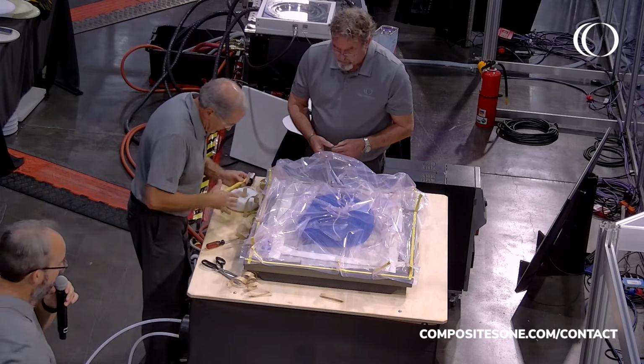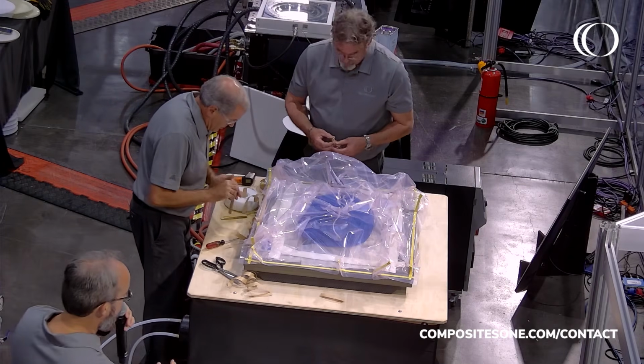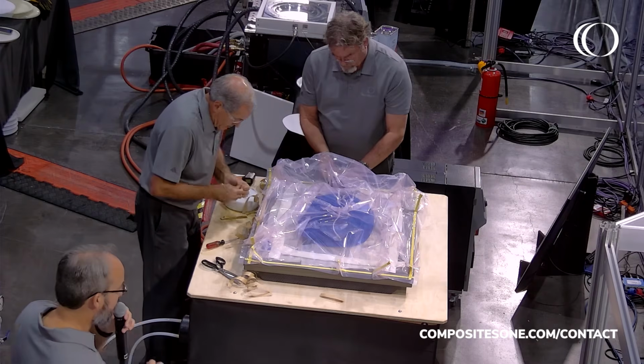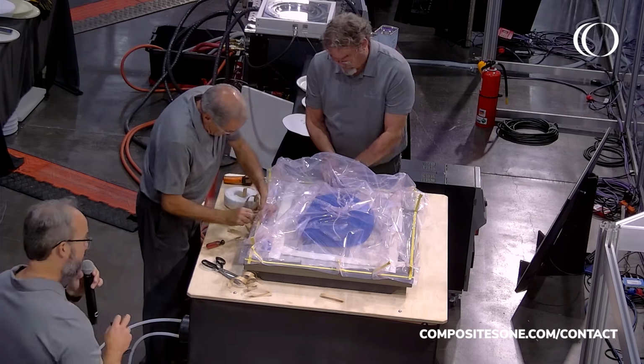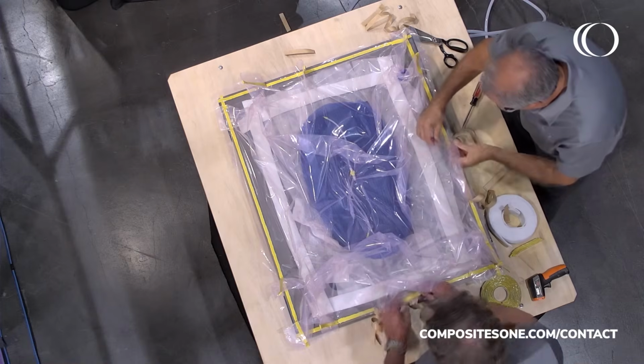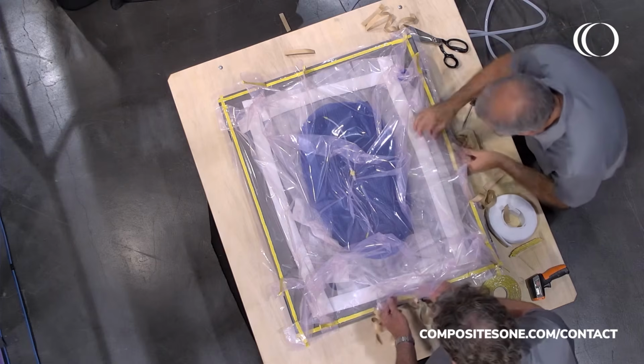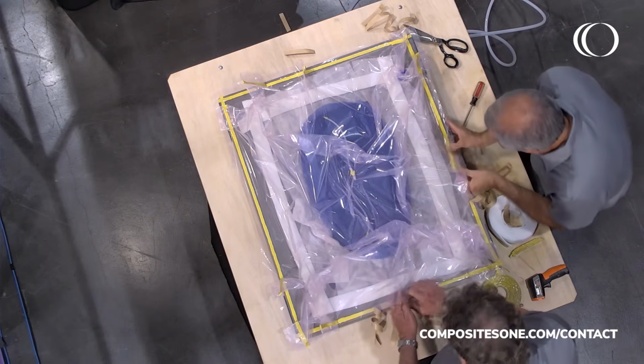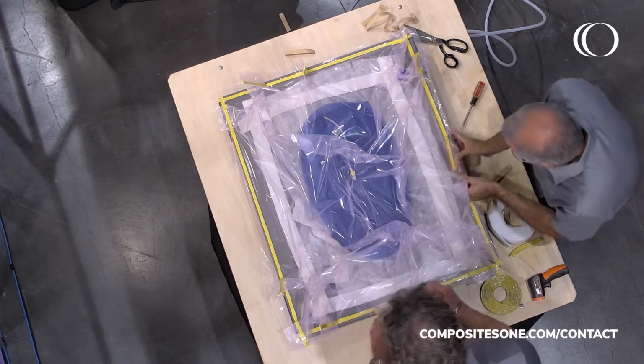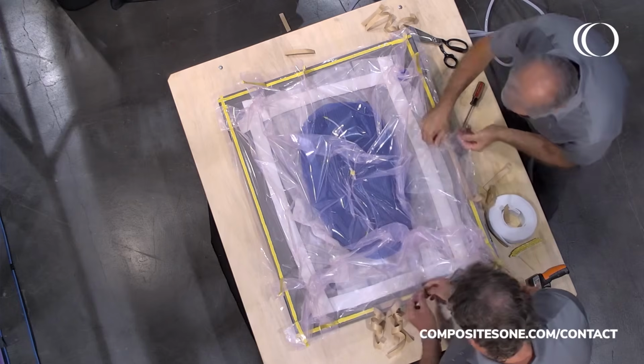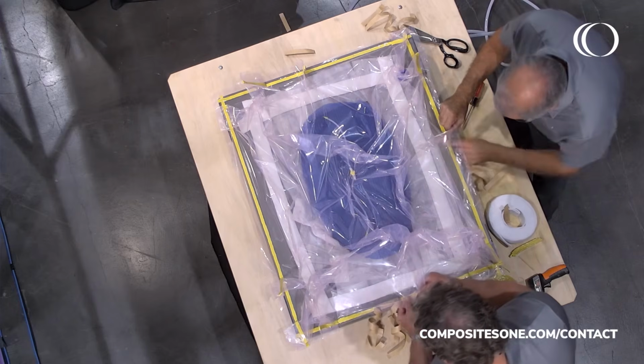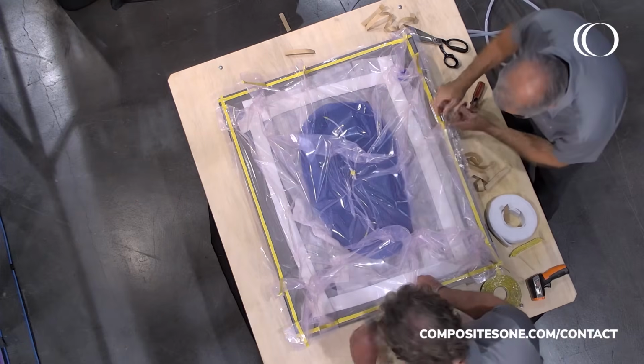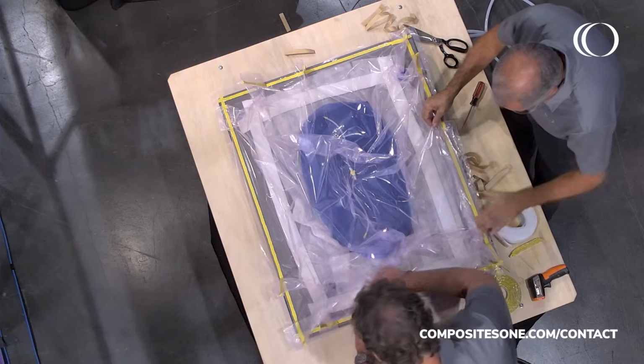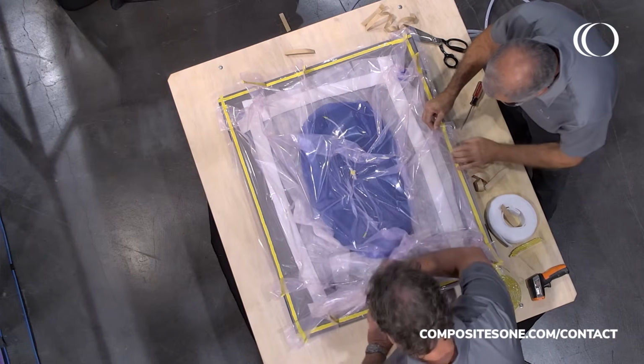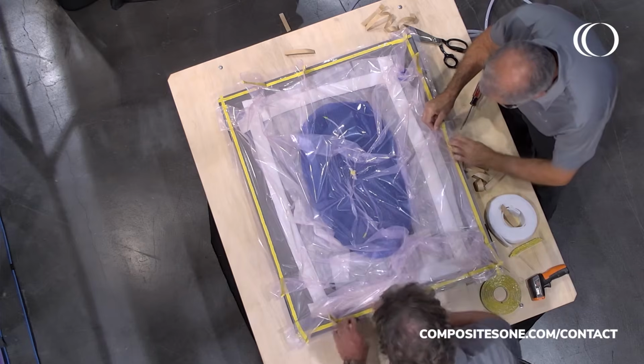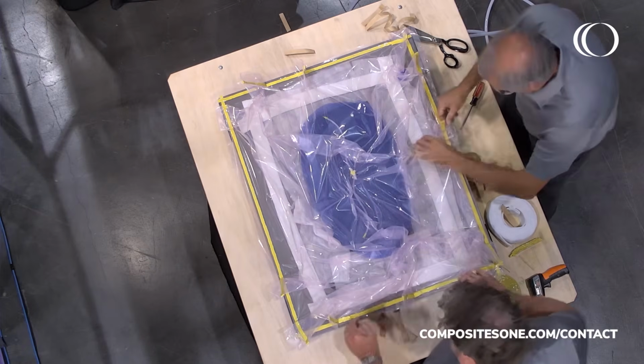Basically, they have the flow media, and you'll notice it doesn't go all the way to the edge of the part. We have kind of a resin break, if you will, so that the resin along the mold surface and in the InfuPly can catch up, and we won't have any lag between the top and the bottom. And then our peel ply provides sort of a resin stopper to slow the resin down so we don't pull all the resin out of our part.